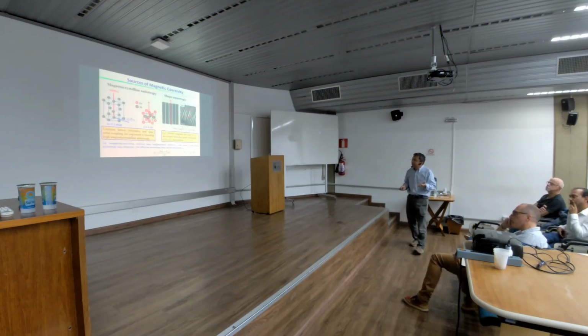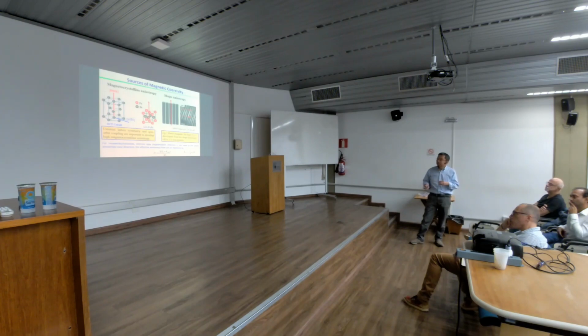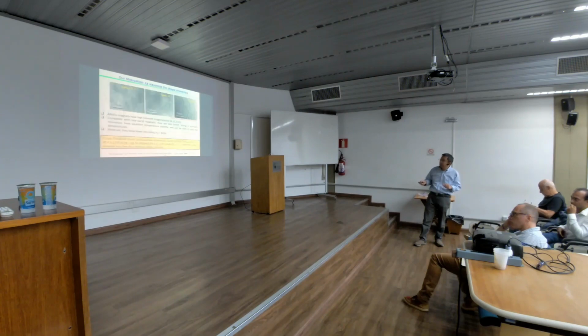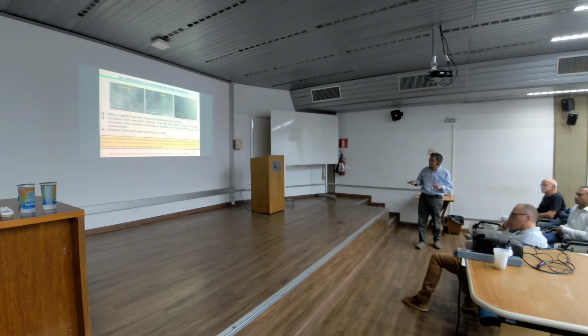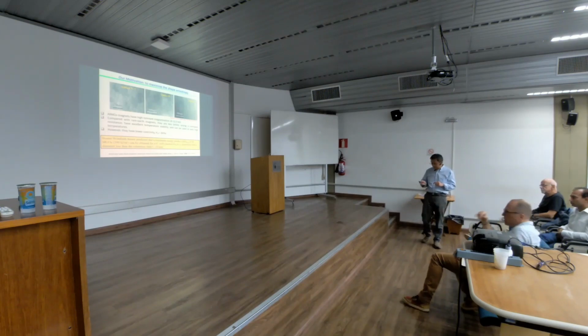And where does the coercivity come from? First it comes from the so-called magnetocrystalline anisotropy, which is based on the crystal structure symmetry. If you have a crystal structure with low symmetry, you have a good chance to develop coercivity because there is crystalline anisotropy. Or you make your sample with shape anisotropy. A good example is alnico. Alnico materials are based on shape anisotropy. However, the coercivity is quite modest, smaller than 2 kilo-oersted.